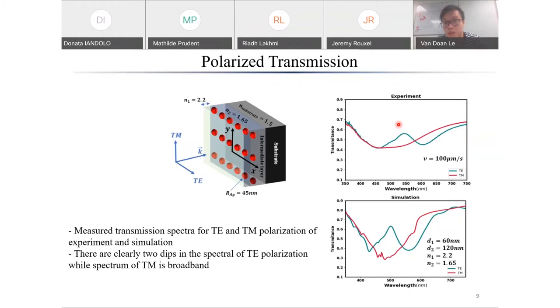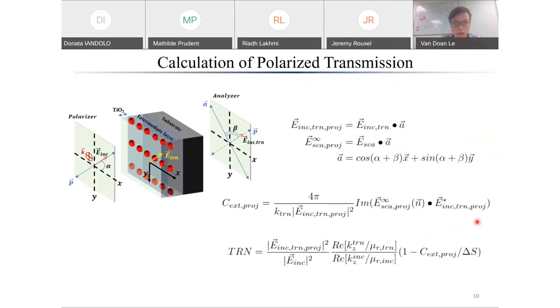For the simulation result, this is the parameter: D1 is for the TiO2, the first layer, the titanium oxide layer, and D2 is for the intermediate layer. I want to show the calculation for the polarization transmission first before the result. The equation is the same as previously, apart from that before taking the two electric fields, I have to project them onto the analyzer, represented by the vector A here. I have to project the transmitted, incident and scattered fields onto the analyzer vector before I take the dot product to get the extinction cross-section, and then I calculate the transmission from the extinction cross-section.